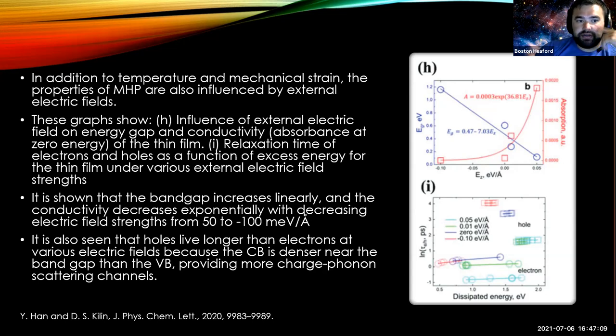And we can see here that the band gap increases linearly as the electric field decreases and the conductivity decreases exponentially with decreasing electric field. It's also seen that holes live longer than electrons at various electric fields because the conduction band is denser near the band gap than the valence band, which provides more charge-phonon scattering channels. Any questions on this one?